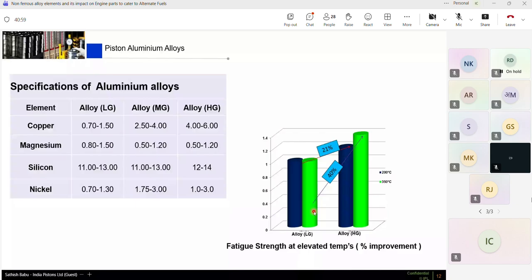So about the piston aluminum alloys, of course, we have different grades of alloy. I did not disclose my material name here. We had a low-grade alloy those days used in Euro 3, Euro 2 emission norms, where the engine power density did not call for any high power, high torque conditions in passenger car, diesel and petrol engines. Of course, in the Maruti 800 and other small engines, a very high grade material was not required. So we started with a normal eutectic alloy, which has 11 to 13% silicon with nickel content of 0.7 to 1.3, and going to copper and magnesium. So with these characteristics,